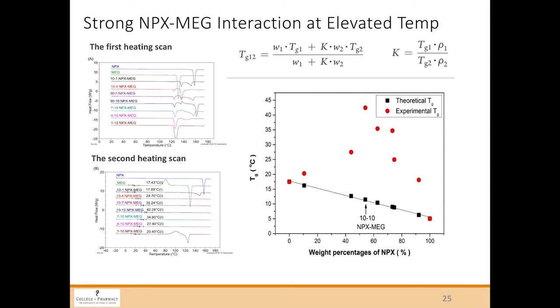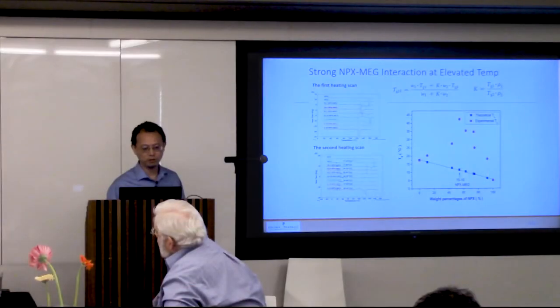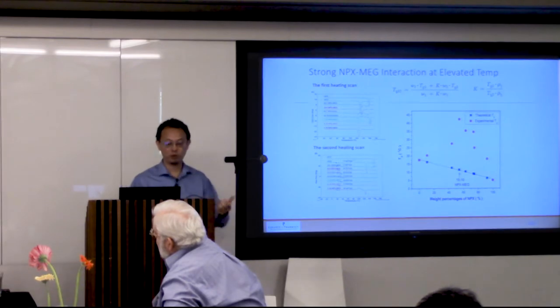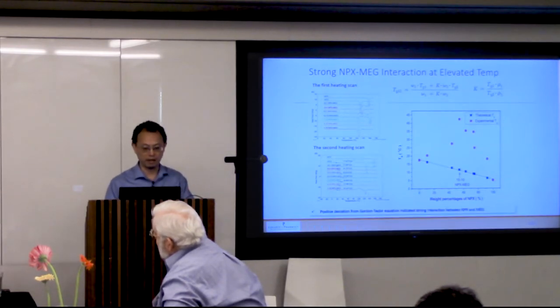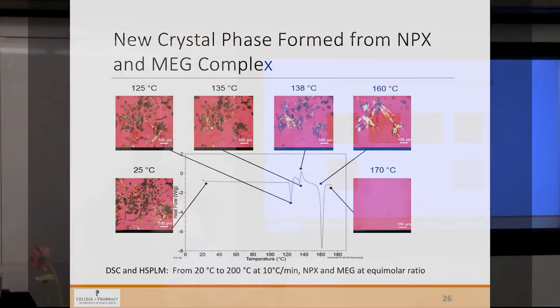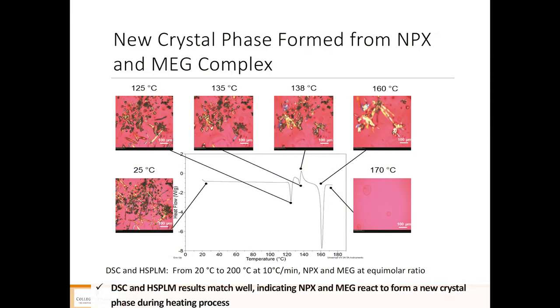When we measure the glass transition temperature as a function of naproxen percentage in the naproxen-MEG mixtures, it's a positive deviation. So that's indicative of a very strong interaction. Again, it's an acid-base interaction. If you look at the hot stage microscope, this is room temperature. Once we heat at this point, there's a melting point depression.